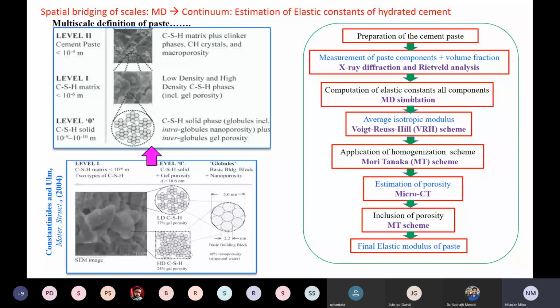And then we did a molecular simulation in order to find the elastic constant for each of those materials. After that, we applied a mixing type of theory, which is called Mori-Tanaka theory in this case. We applied Mori-Tanaka theory in order to find out the elastic constant for, let's say, the cement. And we performed ultrasonic investigations in order to calculate the elastic constant experimentally. And then we matched that the elastic constant that we're observing from the experiment matches with the elastic constant that we're observing from our simulations.